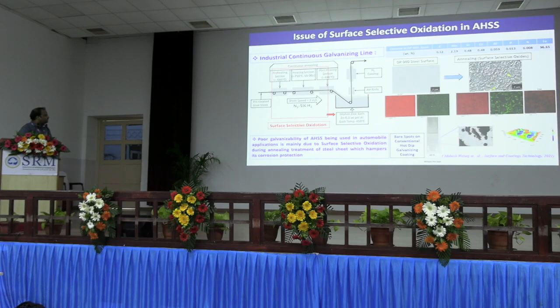But the main issue is that during annealing treatment, the alloying elements which are added from the microstructural point of view cause surface selective segregation and oxidation, and they form tiny islands of oxides. Because of that, it hampers the reactive wetting of the molten zinc on the steel surface and causes uncoated spots.